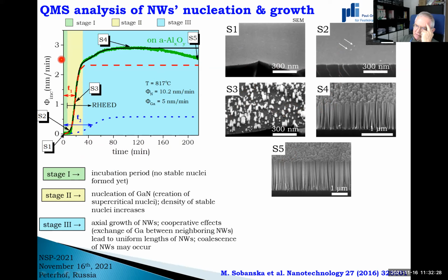The first one, which is marked here in this green field: there is no incorporation of gallium into gallium nitride at all. So if we have a look at sample S1, which was grown for a very short time before the increase of the QMS signal, there is nothing on the surface. But as soon as the signal increases, we see the first nuclei that appear on the surface. So the first stage is the incubation period.